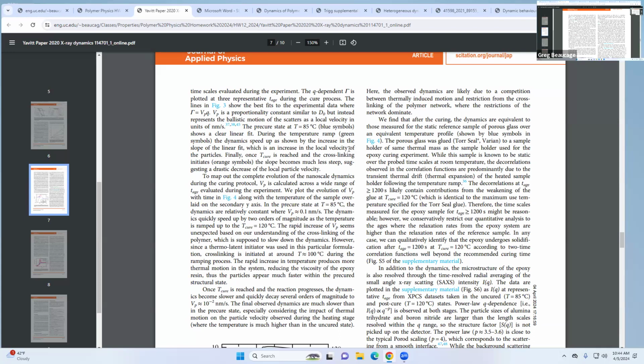So what we do in these experiments is we start at a high dose, and we see this artificial decay in our dynamics because we're burning our material. Then we start lowering the dose progressively until we see a point where our dynamics are independent of the amount of photons, or the dose, that we're giving our sample. So we have to go through this whole cycle of testing those dose-independent dynamics so that we know what we're getting. You may ask, why don't you just blast it with full power? Well, if you blast it at full power, you can see a lot, right? You have a lot of photons coming through, your signal's really good. As I decrease my dose, my signal starts looking worse and worse, and it's harder to pick out those structural features because I just don't have enough intensity. So that's the trade-off.